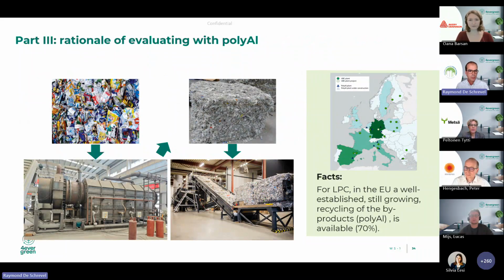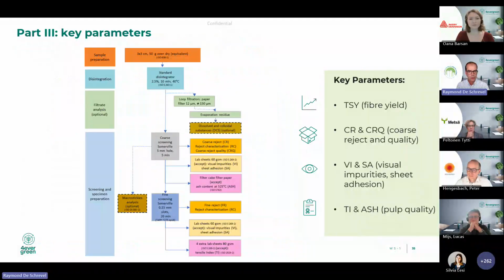Just to show you that it's not a fairy tale, on the left you can see a bale of beverage cartons, liquid packaging cartons that's going into a paper mill with a specialized process. There the fibers will be separated from the polyAl, and a bale with polyAl will go to a next step recycling called a polyAl recycler. And on the map that's also available within 4evergreen, you can see that roughly 100% of the liquid packaging carton bales will find its way into a paper mill with a specialized process for LPC, but that also the polyAl is already finding 70% of its amount in a special recycling process. So it's there, it's increasing, and it's going toward 100%. So having said that, it's important, of course, to reward that into the methodology and the scoring.